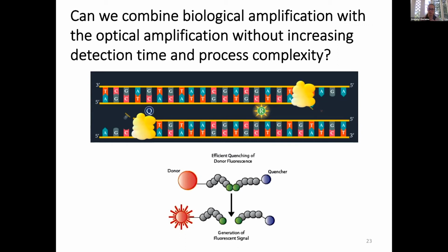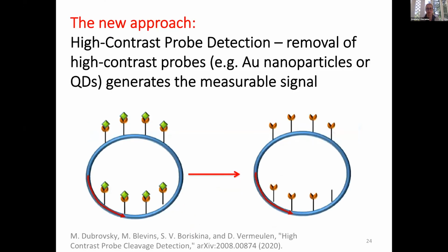So unless you cut this link, and this link cut happens at the multiplication step, you don't see the signal. Once the fluorophore is released into the solution, you can see it. And as more of it is being released, the signal keeps increasing. And that's why after 30 or 40 cycles of PCR, the detector can reliably see a lot of light and detect the presence of the COVID. But in this case, it's not amplification, it's actually suppression, which is then removed. And we felt we could do better. It's always better to amplify rather than just suppress and then return to the original situation.